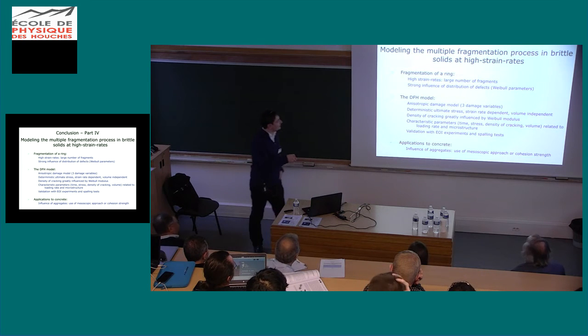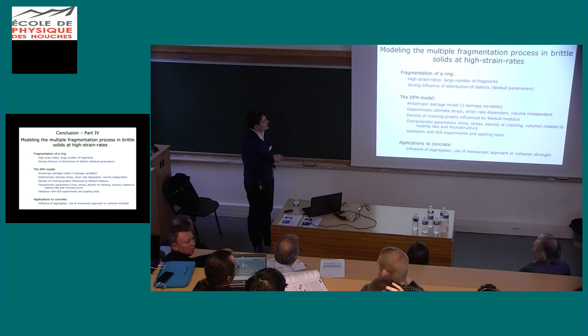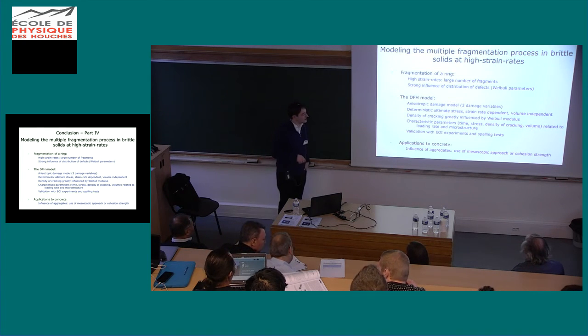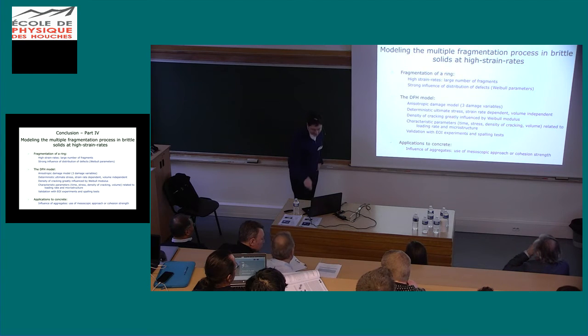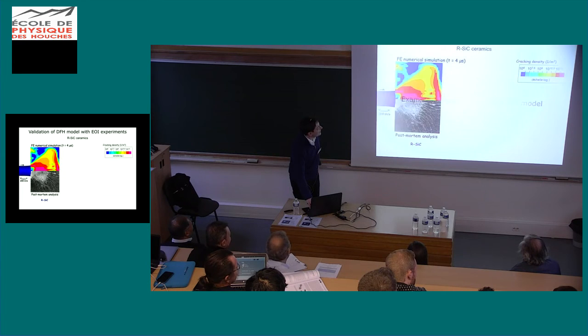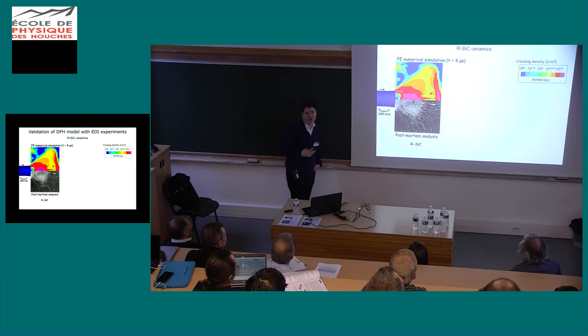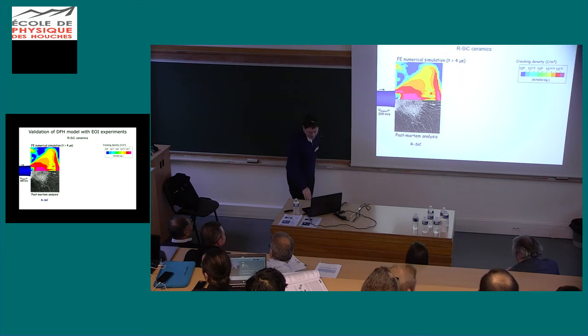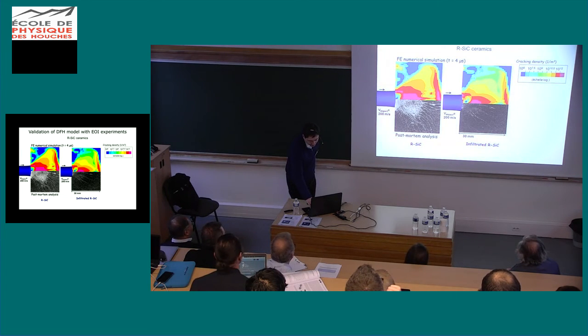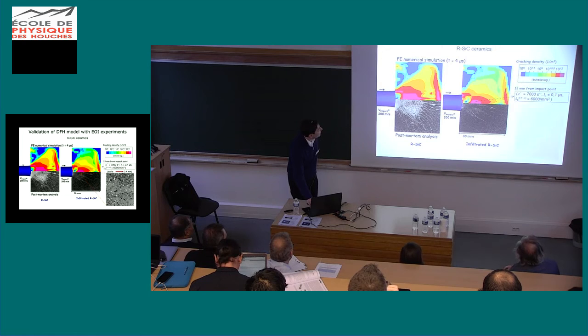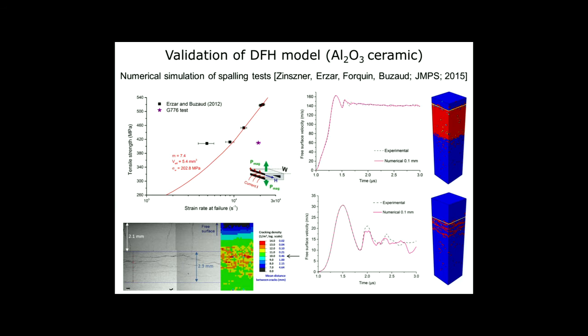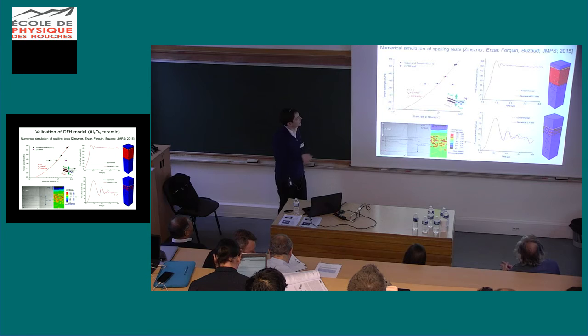Just to conclude with this part, with the DFH model, you understand it's an anisotropic damage model that predicts the strength increase with strain rate and the cracking density given the applied strain rate. Okay, we have performed several validations. I have been talking about that previously, so I will go fast. But one way to validate the model is to perform edge-on impact experiments and to compare the obtained cracking density. One way also is to compare the results with the spalling test results.